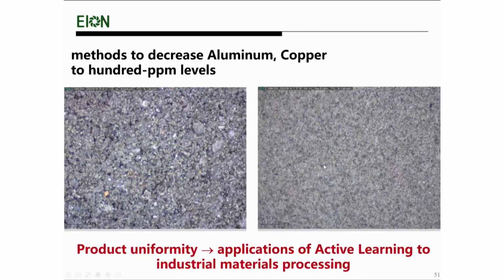That's under development. And lastly, I just want to say that there's a lot of issues with how to remove the impure elements, such as copper, which requires you to reduce it down to 100 or even 50 ppm levels. And not all the copper actually are in the zero valent form from the current collector, because you could have corrosion products that drift from the anode to the cathode. So we have also developed methods to do that.